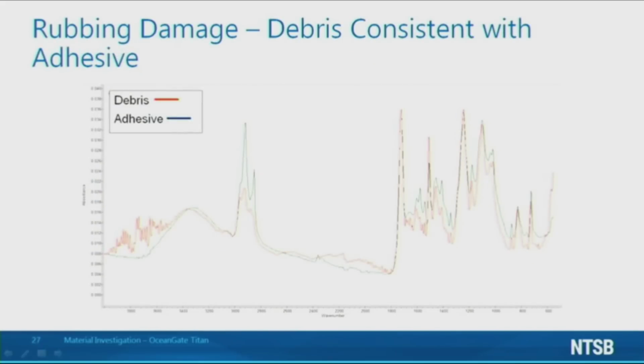The debris was collected and its chemical spectrum was analyzed along with a sample of the green film adhesive. As seen in this image, the debris and the adhesive had similar spectral peak positions and relative peak intensities.